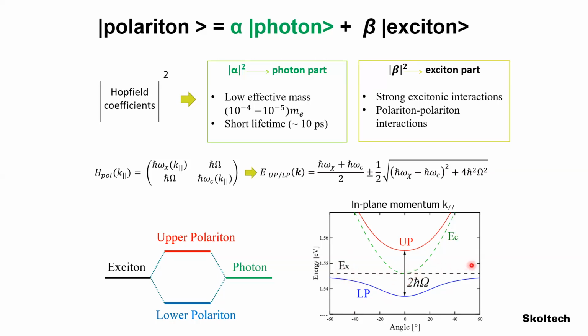Now, strong coupling does not occur only at normal incidence, it occurs at every wave vector. And now if I couple this point with that point, I get these two new modes. Therefore, the system has now a new dispersion, which we call the upper and the lower polariton dispersion. And these dispersions look very different from the bare modes.